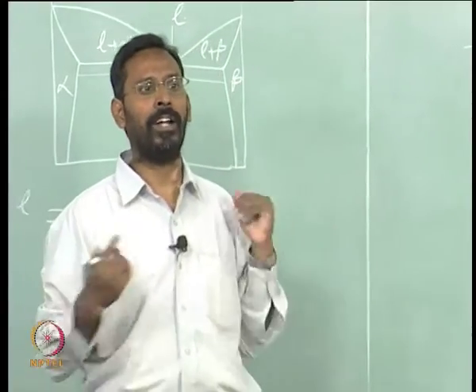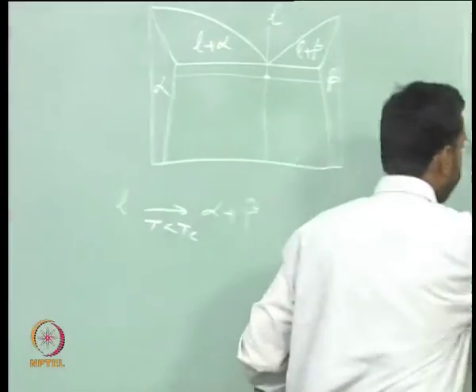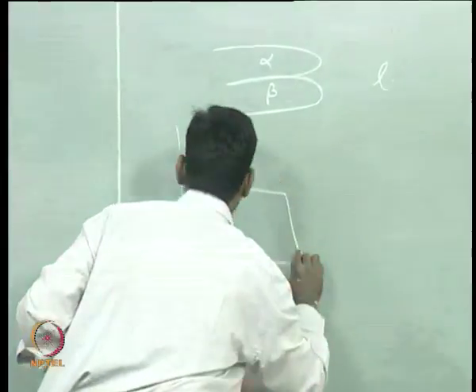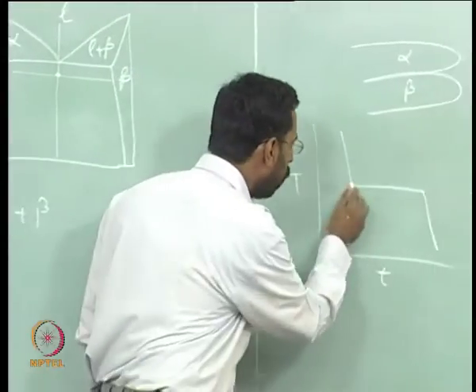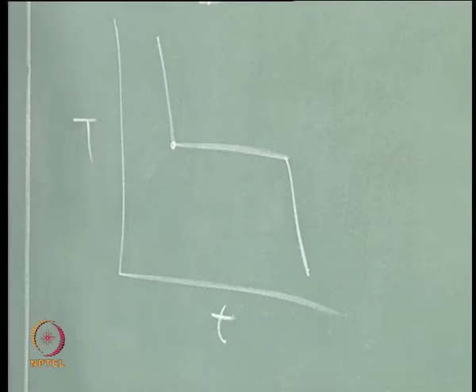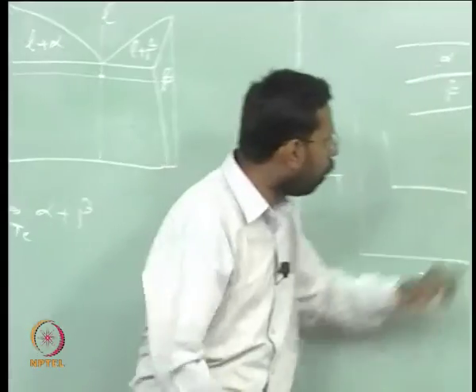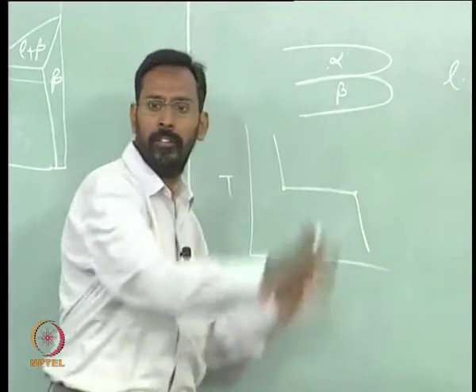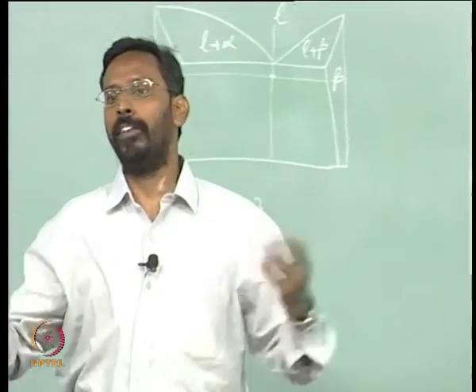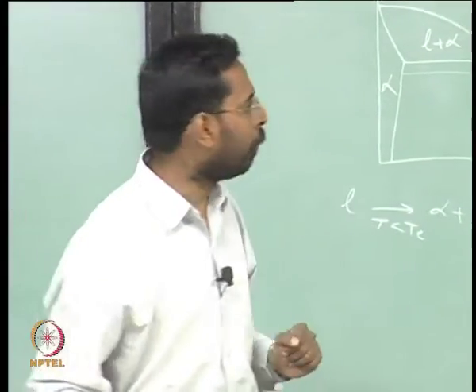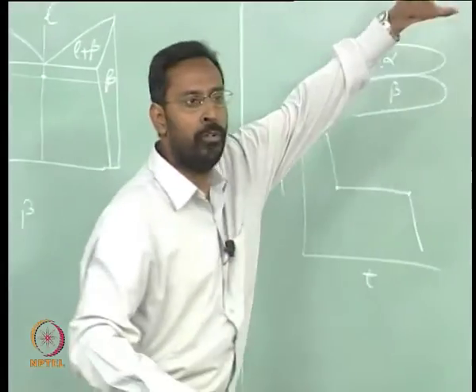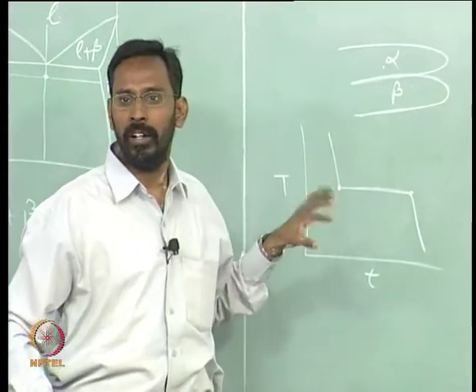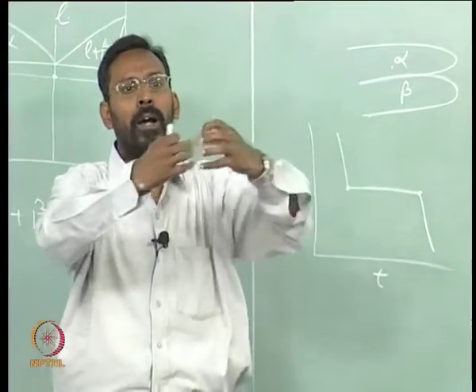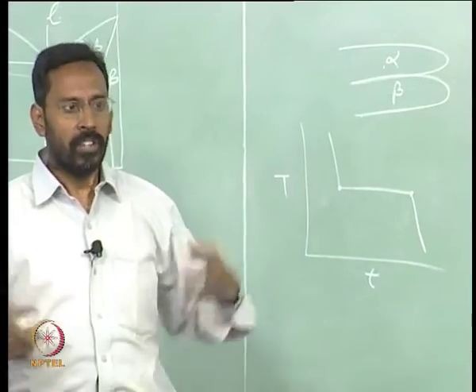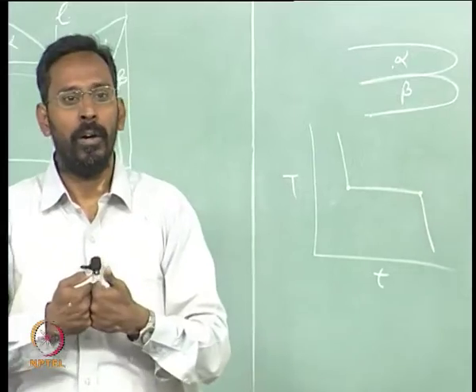So that at the end of the reaction, if I do what is called the cooling curve, temperature versus time, at this particular time this has nucleated, and as I grow by this time all the liquid should vanish and everything should become alpha plus beta. Of course there are a number of such couples nucleating at various positions, a number of nuclei, and all of them grow together, such that they form what are called certain boundaries.